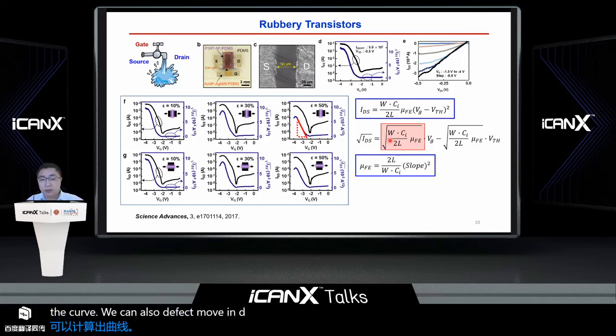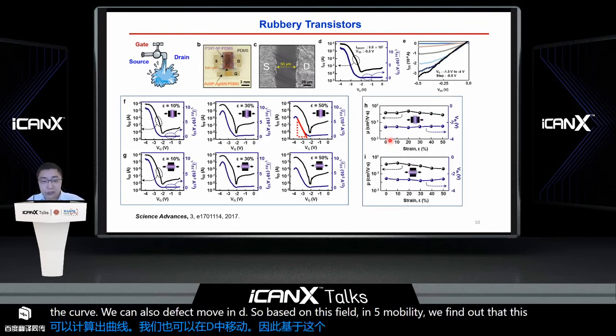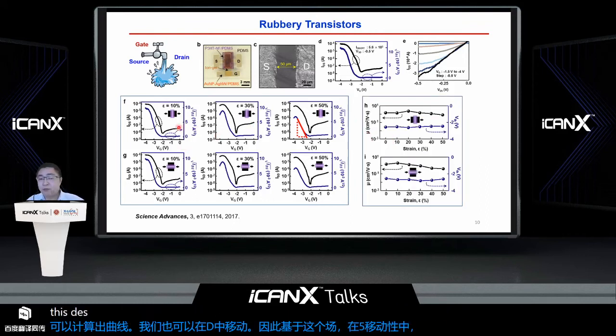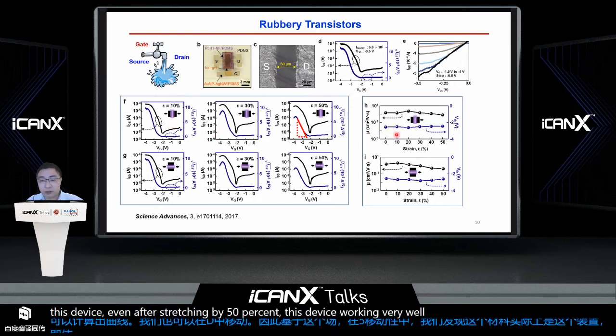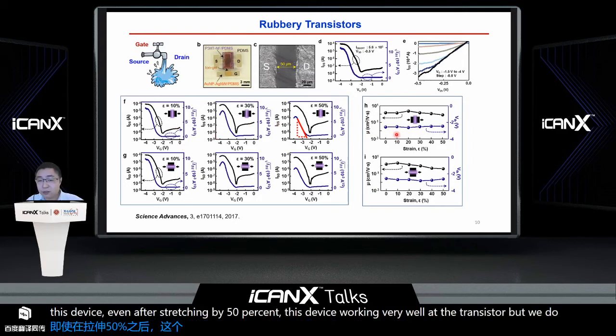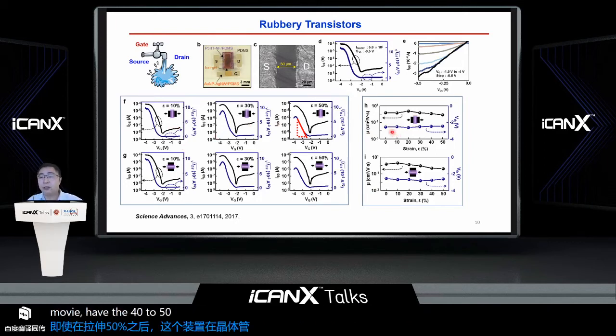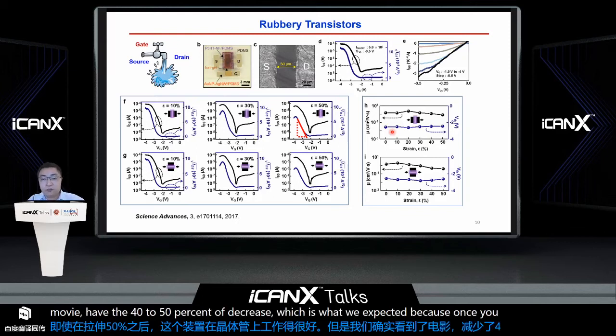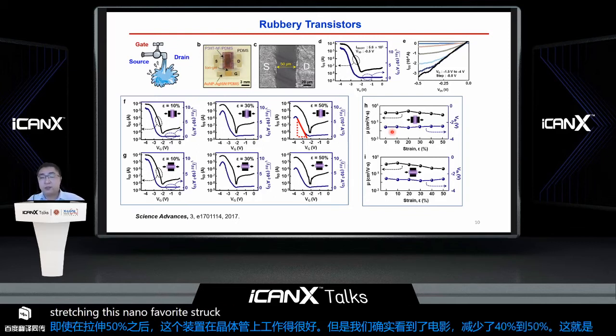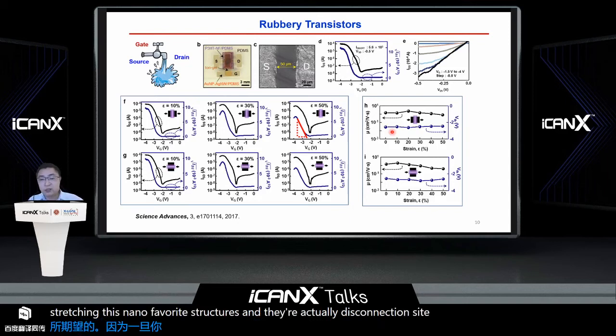Based on this field effect mobility, we find that even after stretching by 50%, this device works very well as a transistor. But we do see the mobility has a 40 to 50% decrease, which is what we expected, because once you mechanically stretch these nanofiber structures, there are disconnection sites that eventually reduce the transport efficiency, so the field effect mobility decreases somewhat.